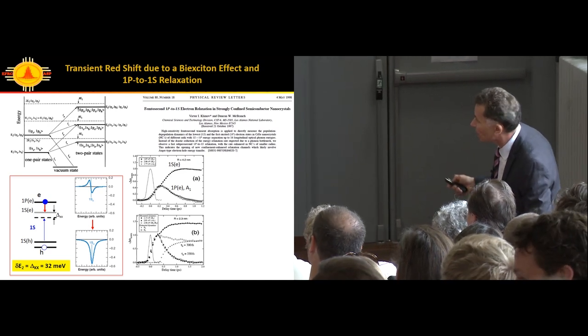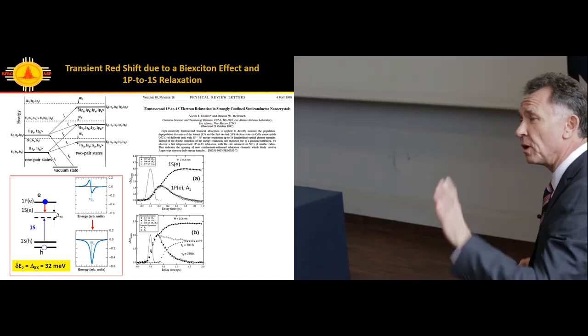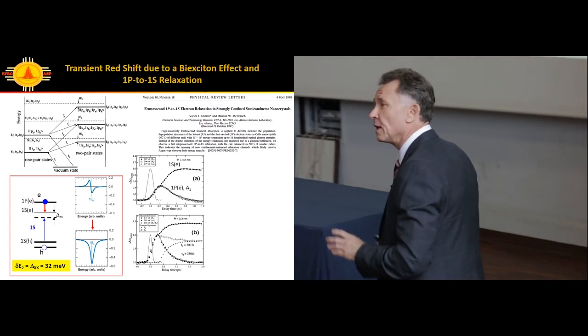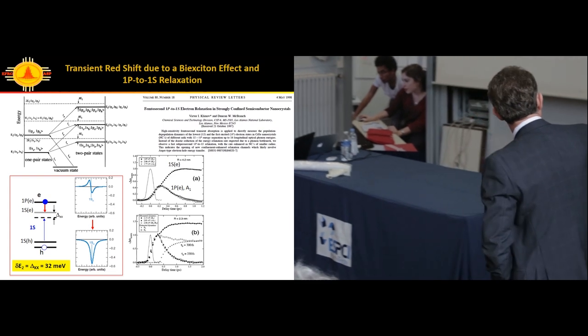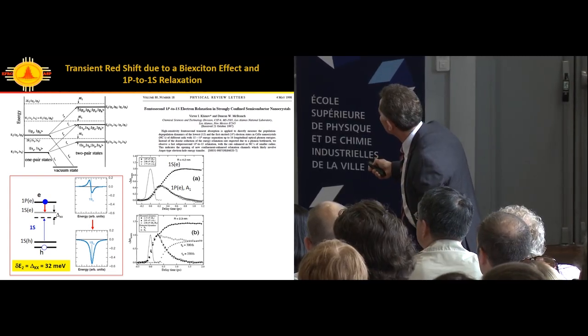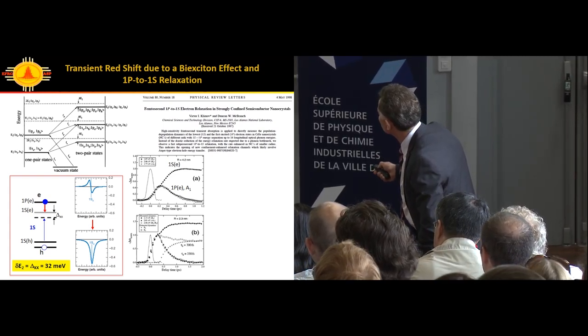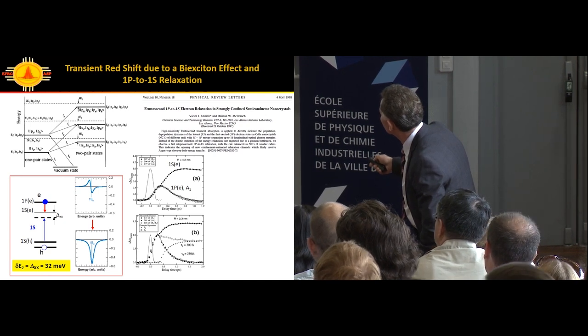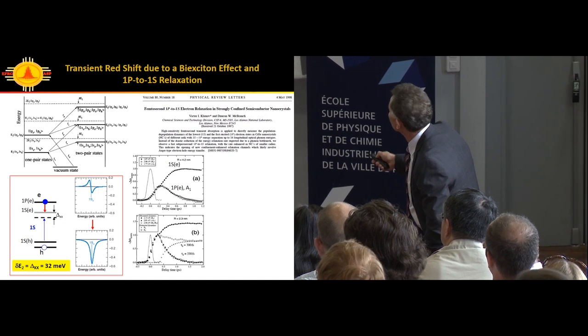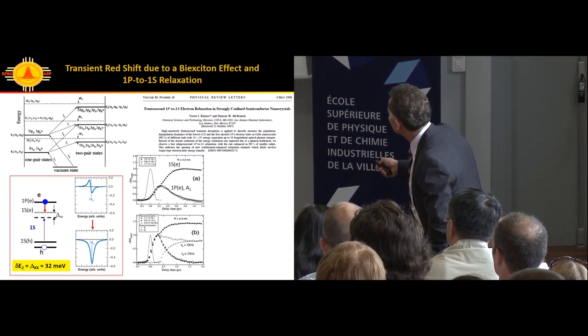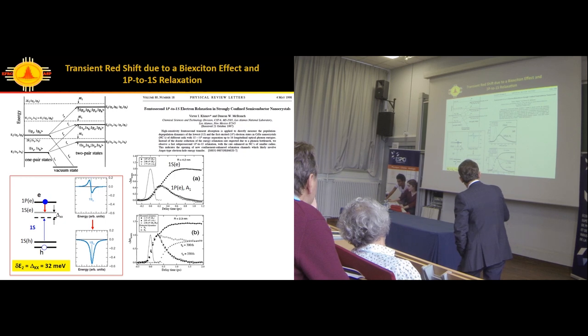These are again looking with TI-Sapphire laser, which I love and still love. Second harmonic of the TI-Sapphire laser exciting the sample, looking at intra-band relaxation. We're looking at the buildup. 1.2 picoseconds buildup of the bandgap absorption feature. Bandgap bleach, complementary relaxation of the 1P state.